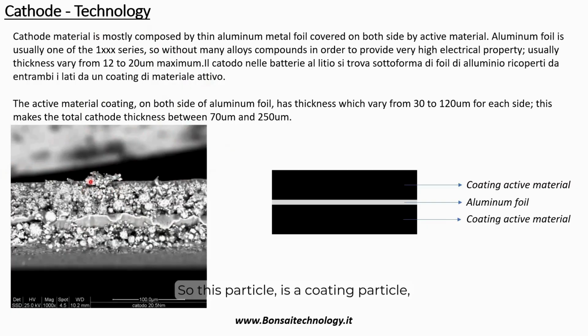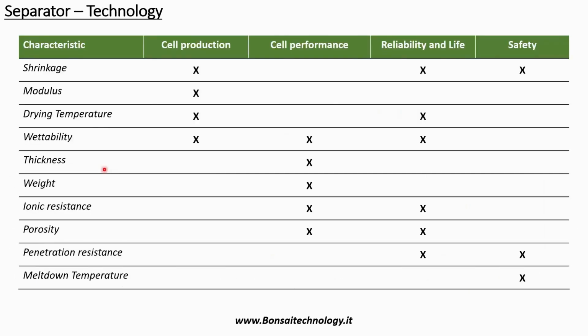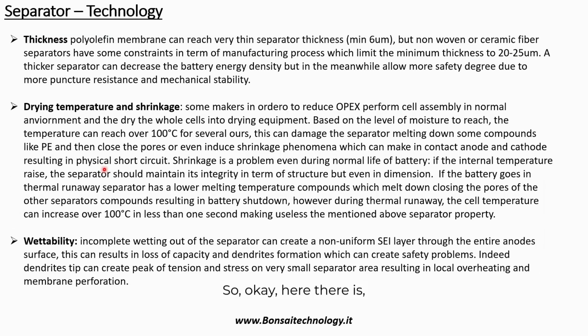So this particle, that is a coating particle, apply a certain pressure, local pressure on the separator with a certain force. If this force is enough to pass through the separator, this cathode will be in touch with the anode that is to the other side of the separator, and this creates a short circuit. These are very, very bad things, because this can start the degradation effect, the thermal runaway, and your battery can get fired. So this is the reason why the puncture strength is very important. So here there is explanation about what we talked before.